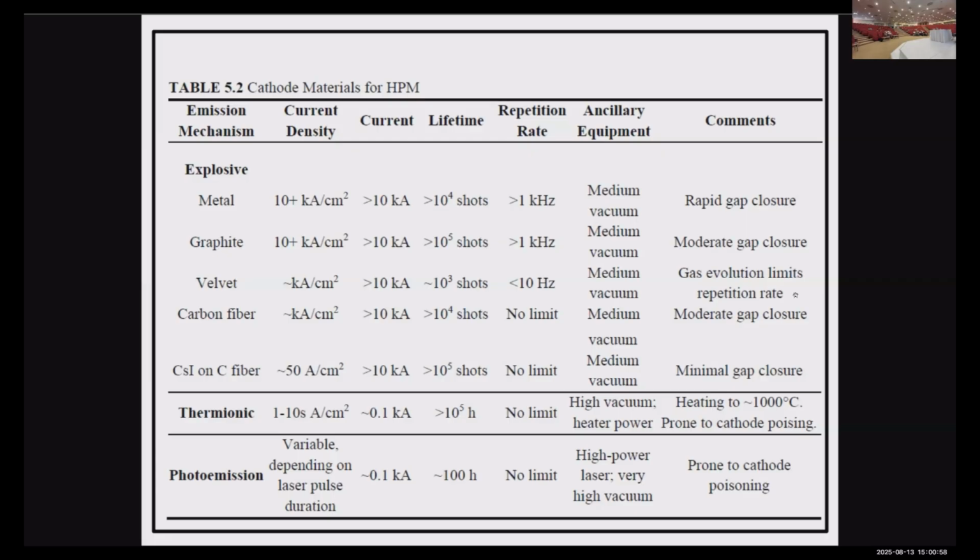If you have some coating on your graphite, this can help you have a slower plasma expansion, and that's why they use some sort of coating around it. Also, if you have your graphite emitting, after a couple of pulses you'll start suffering from non-uniform emission points. So your beam is not uniform. It has some hot spots and some less dense spots, and this is going to reduce the microwave source efficiency. So they use fiber to improve this.